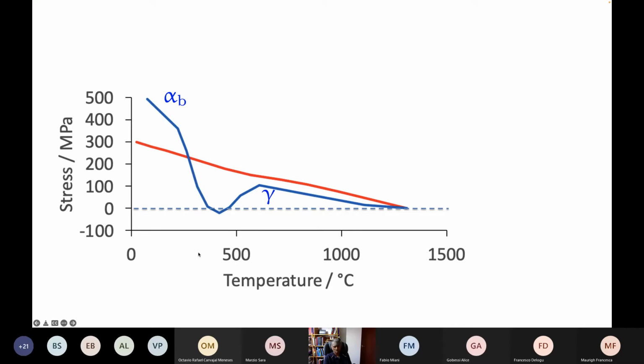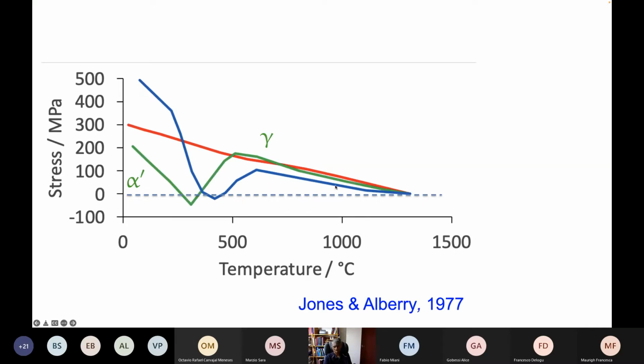Okay, so what happens if we lower this transformation temperature? So instead of bainite, if we now produce martensite, once again, the same phenomenon until we get phase transformation, we cancel out the effects of thermal contraction, and because the transformation is exhausted at a lower temperature, we end up with a smaller residual stress. So this gives you an idea on how to design a welding alloy that would leave your component with a zero residual stress at ambient temperature.